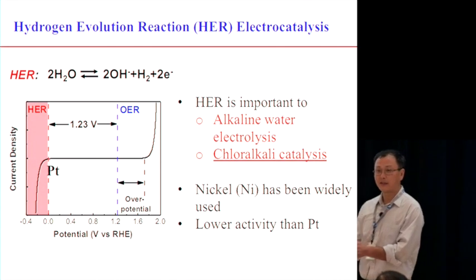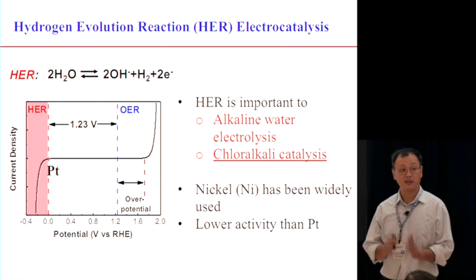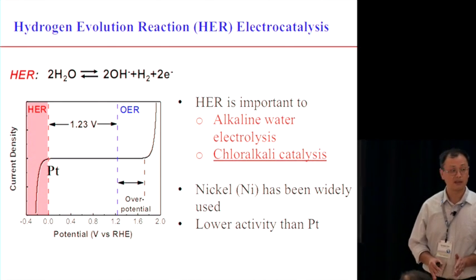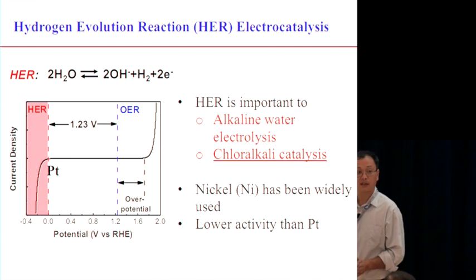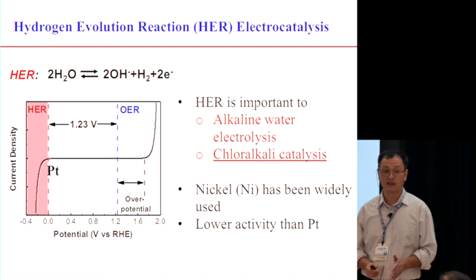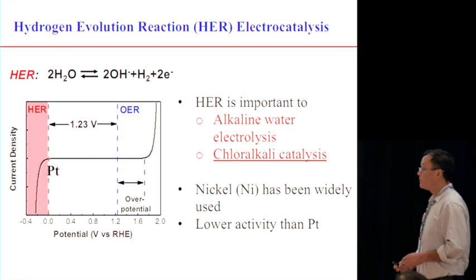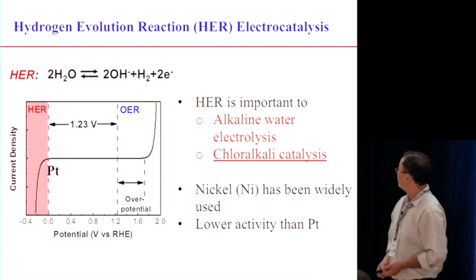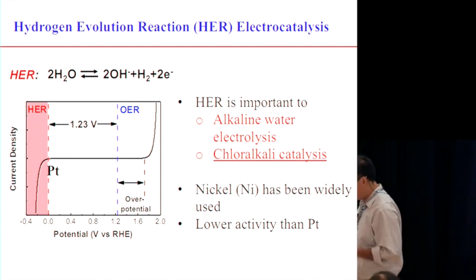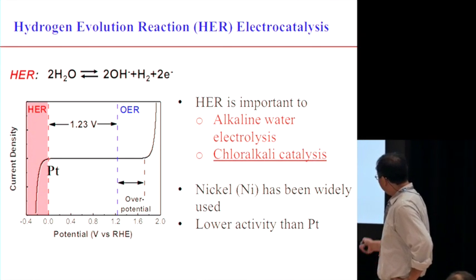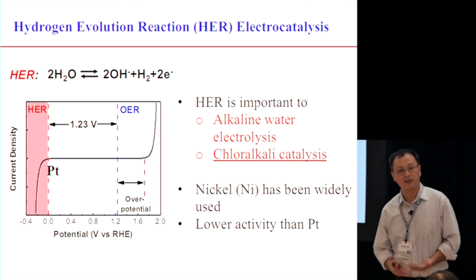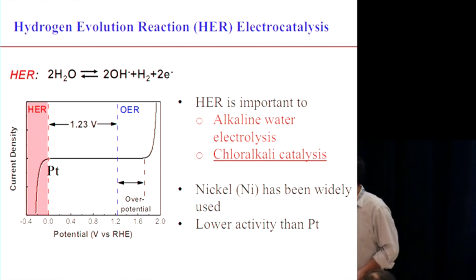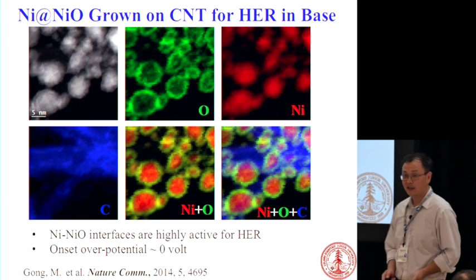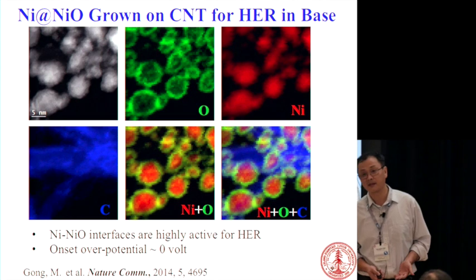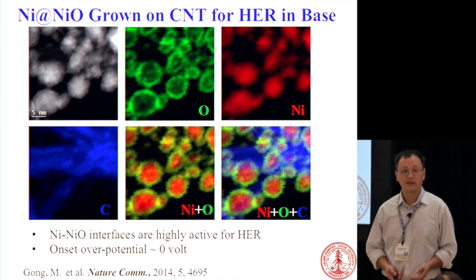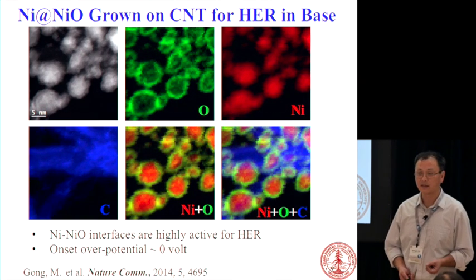So one side you produce chlorine, the other side you need to produce hydrogen. And this is an extremely energy consuming process. Okay, it actually consumes about 8% of the electricity in the United States, 8%, just for this single reaction. So you do have a need actually to lower the energy cost or the overpotential for hydrogen evolution. And so far, in industry, nickel is the metal that's used for HER, okay, in basic solutions. So recently we found that you can actually do better than nickel, okay, if you make a material that contains nickel and nickel oxide, okay.